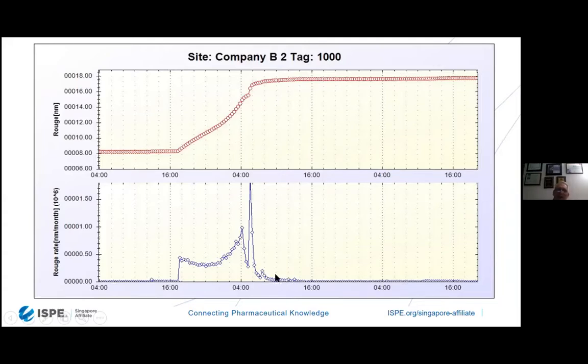And the reason for that is the sodium hydroxide and the chemicals remained in the system for a longer period of time than was even shown on the conductivity. So actually, when these people tell you that everything is done with the system after 3 hours, as far as the chemical application and cleaning and doing the derouging and passivation, that is actually erroneous. It's not true, and shown specifically by the data here.